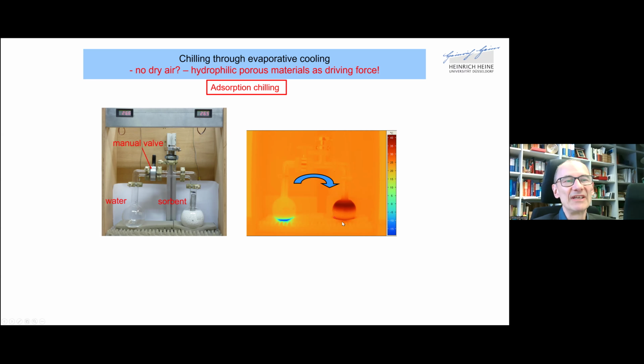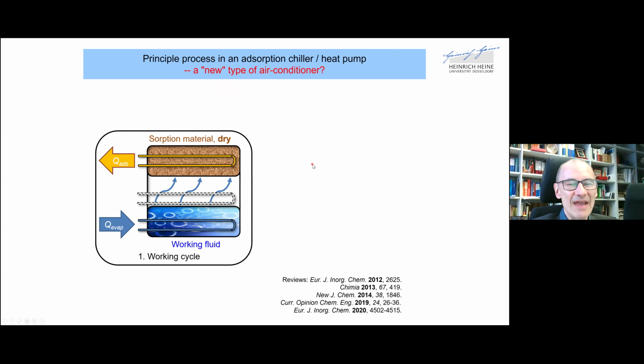And because of the heat of adsorption, the sorbent-filled flask turns quite warm. Here it's about 40 degrees centigrade. So this is, of course, initially a one-time process. And in order to make it a technologically interesting process, one has to turn it around. So how can we turn it around?